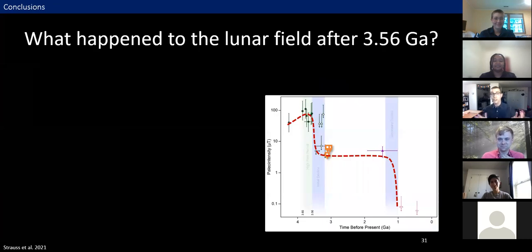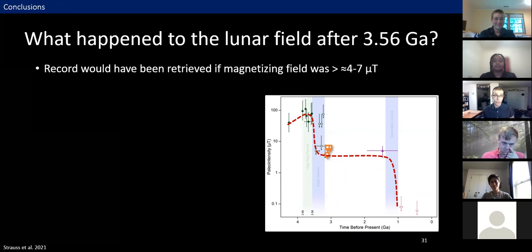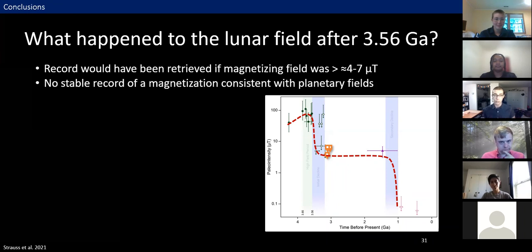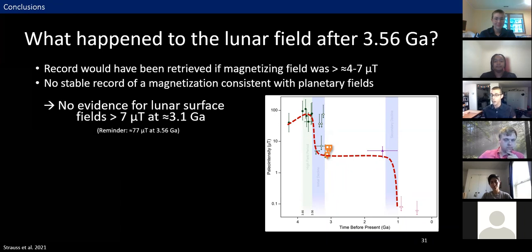What happened to the lunar field after 3.56 billion years ago? Well, we would have been able to retrieve a record of that field if it was any stronger than about 4 to 7 microteslas. However, we did not retrieve a stable record of a magnetization consistent with that kind of planetary field. Therefore, we find no evidence for lunar surface fields any stronger than 7 microteslas at about 3.1 billion years ago. And as a reminder, that's roughly an order of magnitude drop.